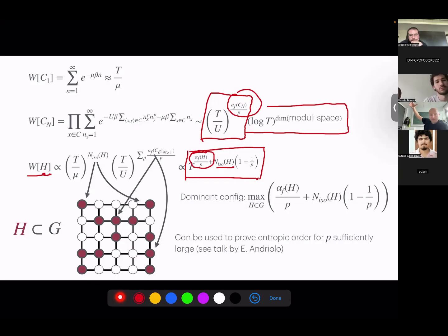So now the question is, which configuration is maximal? Well, the most dominant one is the one which maximizes this exponent. So then you are asking which subgraphs have the highest temperature power, right? So you have a whole graph G and a subgraph H, and you ask which one is the most dominant. And you can prove that if P is larger than 1, and if the graph is bipartite, the graph that dominates is the one of the maximum independent sets. I didn't write it here, but it's basically, on a square lattice, our checkerboard. It's the one that doesn't have any neighbors.